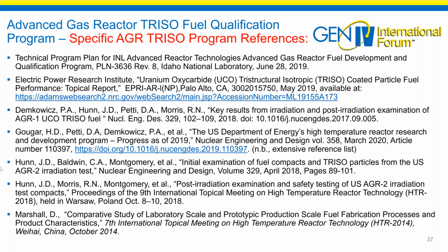Okay. Can we treat the maximum temperature of 1600 degrees C as the safety limit, similar to 1204 degrees C for LWRs? Yes, you could. That's where you have to have it perform, and that temperature was based on the prismatic block design for NGNP, and the block design is a little bit lower in the German tests. The important part of that is